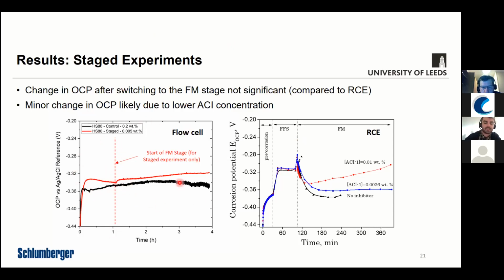As we change, this is just for the red line, and the black line is a control test where there is no changing of tubing. It's just a consistent exposure to 0.2 weight percent. You can see that there's no significant changes. We do see a slight change, but not the same spike. And it's likely that change is just because the inhibitor concentration has changed rather than some fundamental difference.